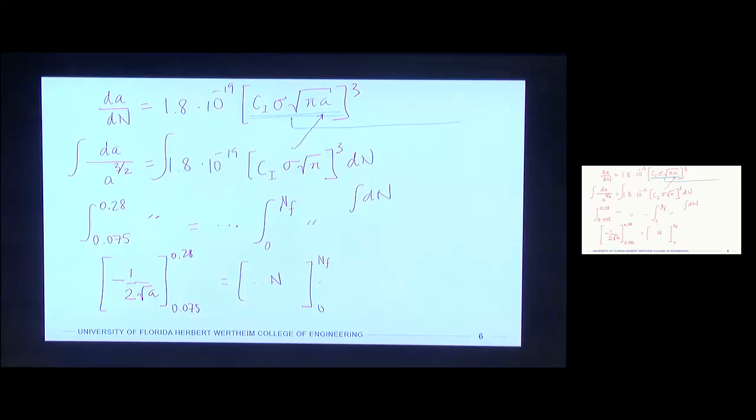Because we have sigma mean, sigma max, all of these things that we had been calculating, right? Because that formula is delta K, right? So one part of the delta K is 0, that's why I think we just use that one. If there was sigma 1, then it would be like C1 sigma 1 root pi A minus C1 sigma 2 root pi A. Ah, yes, okay.